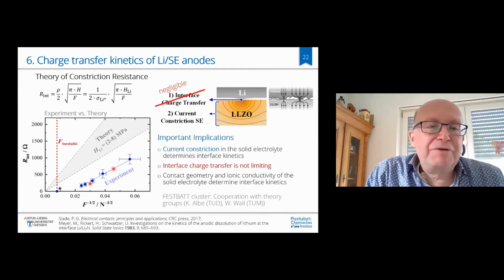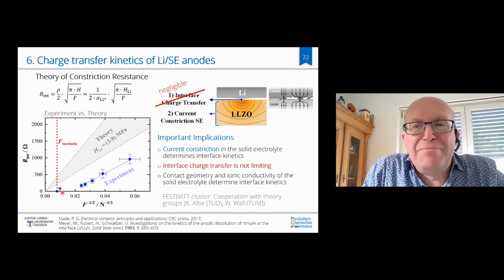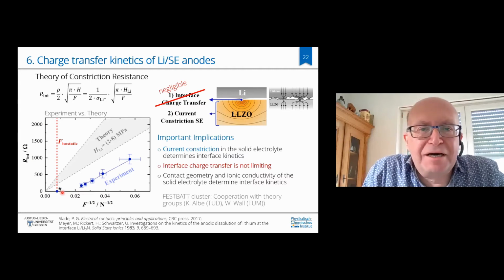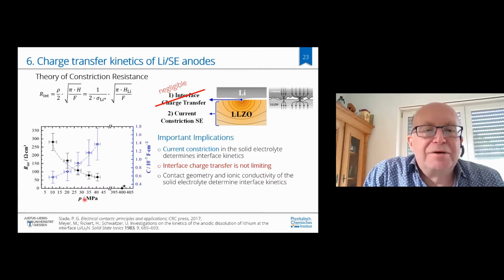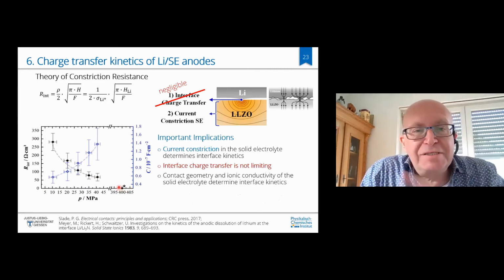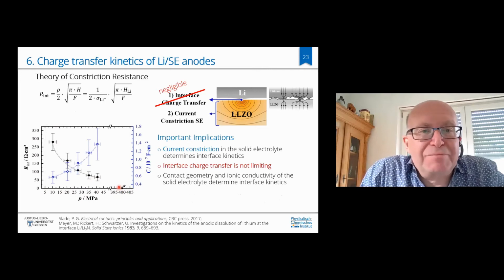And what Torben showed, if you increase your pressure and your force strong enough, you don't see any more resistance. And this is, I think, quite exciting, because that means that the charge transfer itself does not have really a high impedance or a high resistance. So in these experiments, he showed that about 4,000 bar, so 4 kilobar, were required really to see a negligible interface resistance. In a few minutes, I will show in a much nicer experiment with a single contact how low the interface impedance really can get.